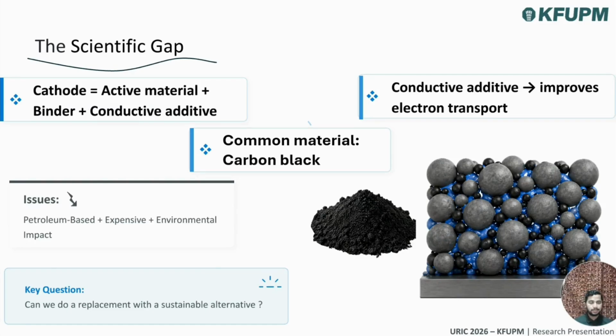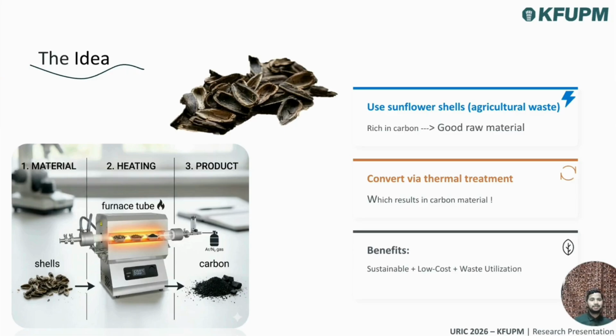So now when we want to discuss the cathode, a cathode usually consists of three main things: the active material, which stores the charge, the binder, which connects everything in the battery, and the conductive additive, which moves the electrons, and the common material is carbon black. Carbon black actually is petroleum-based, which is environmentally harmful, and also it's expensive. So we came up with an alternative material, which is sunflower shells. Sunflower shells are rich in carbon, so they are a good raw material as a replacement for carbon black, and will be converted to activated carbon through a thermal process.